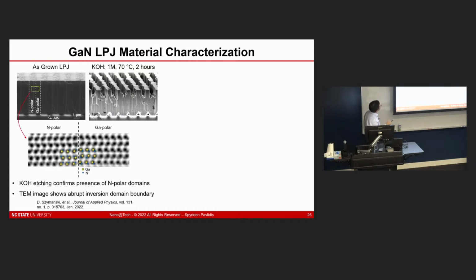And if you zoom in and do a TEM on this cross-section, at this scale, you can see that there's a very abrupt interface between nitrogen polar and gallium polar as well. So these are atomically abrupt inversion domain boundaries as well. Full disclosure, I would say we still have some work to do at a macro scale. You can see there's a bit of roughness along that edge, but at this scale here, there's good control of these inversion domain boundaries.